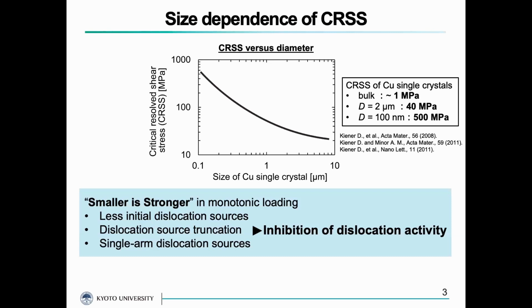The underlying mechanism of the phenomenon smaller is stronger in monotonic loading is considered to be the inhibition of dislocation activities in nano to micro-sized single crystals. In such smaller single crystals, there are fewer initial dislocation sources, and dislocations can be easily emitted from the surface. The activation of single-arm dislocation sources is also considered to contribute to such high CRSS.